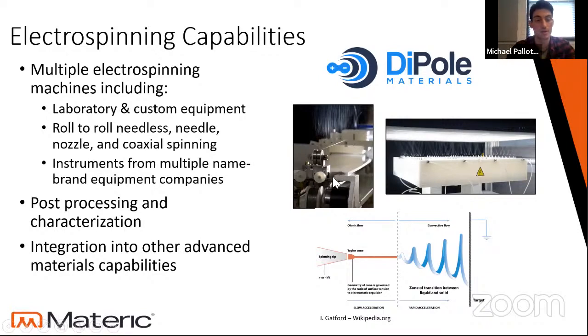That differs from a conventional lab electrospinning setup in that there's no needle through which the polymer solution is being forced and then the electric field is being applied to. This allows for a high throughput of Taylor cones as you're depositing solution onto a wire, which allows for more solution to be drawn up onto your deposition substrate.